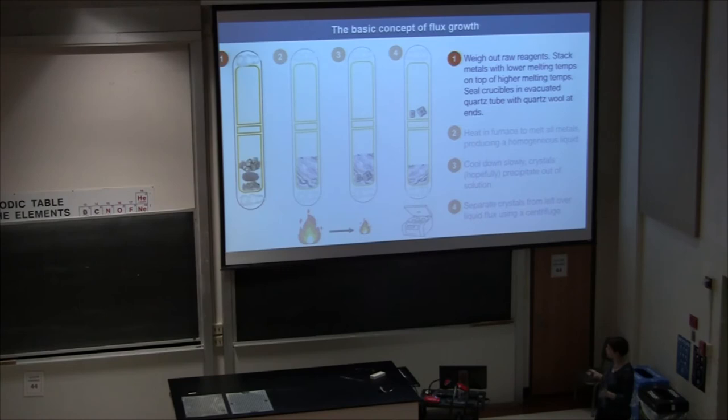You have your two crucibles, so this is crucible one, crucible two, and they're separated by a ceramic strainer. These are the so-called Canfield crucible sets, where instead of putting some quartz wool in between your two crucibles that's going to act as a strainer, you actually have a ceramic that's not going to contaminate your growth. So you've put your metals down at the bottom of one crucible, and you've sealed it inside of a quartz